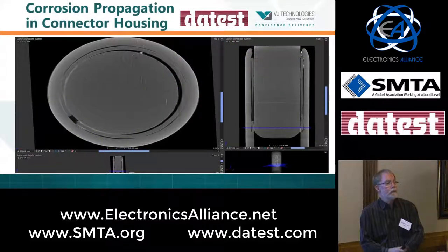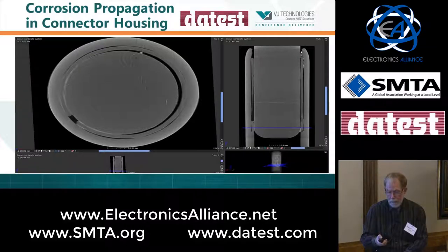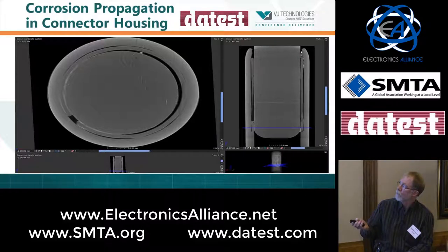This is a connector housing that was used in an outdoor solar array, and it failed. And the customer knew there was corrosion, but he didn't know where. So we scanned the connector array, and we found points of impingement right here, right along here, right along here, right along here. Basically, what you see here is what we're viewing top down right there. And trust me when I tell you that's corrosion. And that was the principal reason for the failure of that solar array.